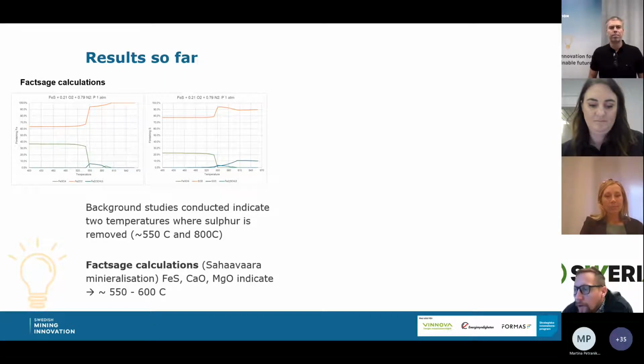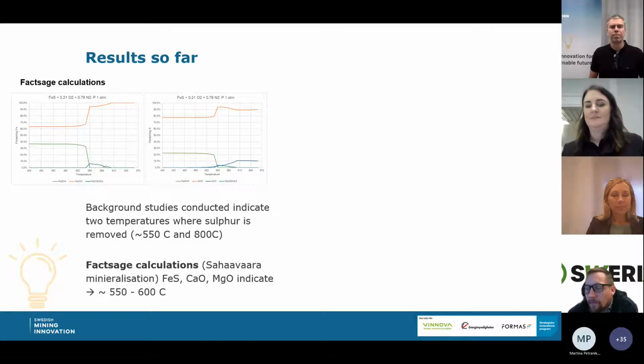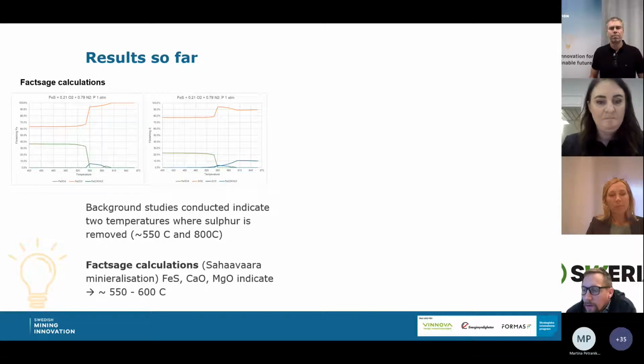So far we have done some calculations theoretically. Based on these calculations, we can see there's a clear temperature where sulfur will be transformed into a gas phase. This happens somewhere around 550 degrees. If we would be able to do this, we would then be able to treat this material without needing a flotation step.